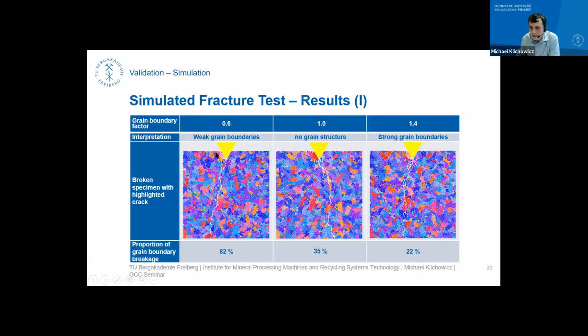This is a DEM simulation of a very thin plate, which is loaded by a chisel in this notch and then fractured. What I've done now is I've mapped this realistic microstructure to this DEM simulation. And then I just varied the strength of the grain boundaries. So if we have a so-called grain boundary factor of 1, all bondings are of comparable strength. So there are no differences in the strength of grain boundary bondings and bondings inside a grain.